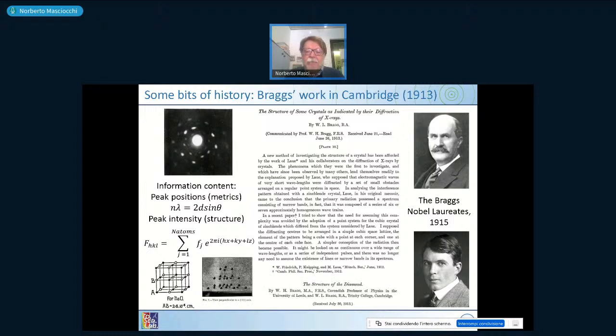Soon after, that means July 30, only 34 days after the first paper, a second paper came out, which is the structure of diamond. So they discovered a tool with which, observing spots on a screen, they could get information on size, shape, and the crystallochemical nature of any principal crystal aggregate. So in two months, they published the first two structures, and since then, more than 1 million crystal structures have been discovered, not by the Braggs, of course, but everywhere in the world.